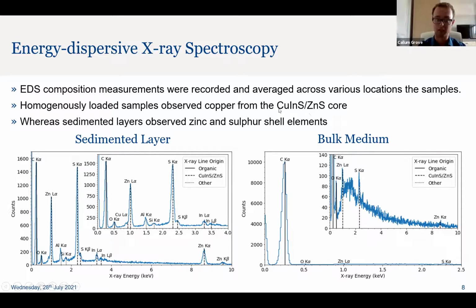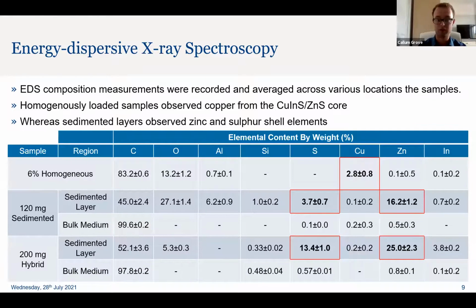Interestingly, we don't get that much core material. There's a limited amount of copper and a limited amount of indium that's available. The reason we think is because we're viewing the shell material around the outside of the quantum dots, and the X-ray or electron beam wasn't penetrating the core and producing X-rays well enough. And then the bulk medium on the side here, there are zinc and sulfur lines, but not anywhere near the same intensity. So we know that there's a small amount of quantum dots in the bulk medium. However, it was very hard to measure that in any real quantity.